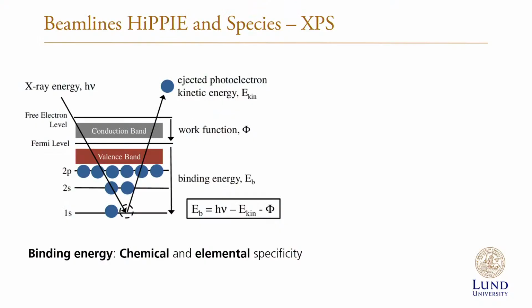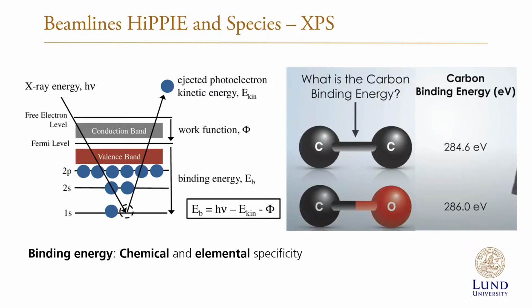For instance, it's species specific, so we know exactly what kind of element we are probing. And it's also chemically sensitive. So depending on the chemical surrounding of this atom, we can get a lot of information about the structure and how these atoms are arranged in the material. For instance, if carbon is binding to another carbon, we can measure that at a specific binding energy, as we call it. But if carbon binds to an oxygen atom, it will show up at a different energy. And by that, we can get this kind of information. That is very useful for catalysis, because then we have the interaction between gases and material, or in this case, plasma and the material.